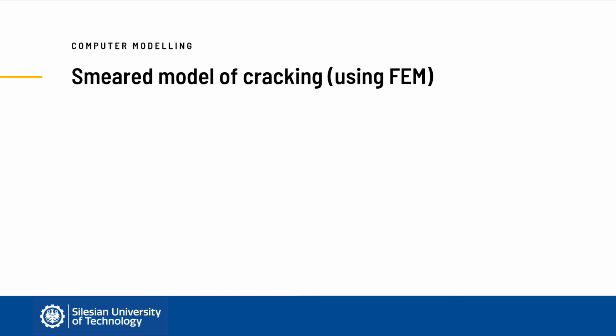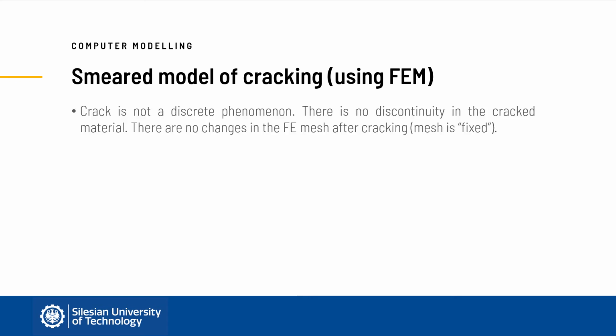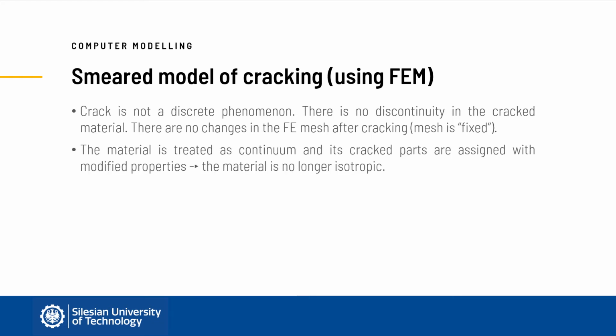For that purpose, the smeared cracking model is employed. In this approach, crack is not a discrete phenomenon and no discontinuity is introduced to the mesh. Concrete in this approach is treated as continuum, before cracking as a homogeneous solid with isotropic properties. After cracking, the cracked parts, or more precisely, cracked finite elements, are assigned with modified properties and the material of the cracked part is no longer isotropic.